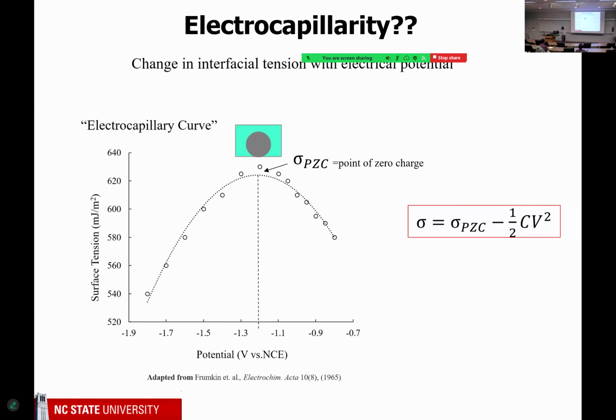Well, our first thought was maybe this is what's called electrocapillarity. This has been known since the 1800s. And so I need to kind of walk you through this, but this is a plot of surface tension on the y-axis, and potential on this axis. And if you imagine you have a droplet of the metal sitting in electrolyte, it's got a very large surface tension. Remember water? 72? This is like 600. It's huge. Well, if you want to trick the metal into liking the water, one thing you can do is apply a potential to it. And if you apply a positive potential, you'll draw negative ions from the water. And if you apply a negative potential, you'll draw a positive. But it doesn't matter. Either way, it will lower the tension.